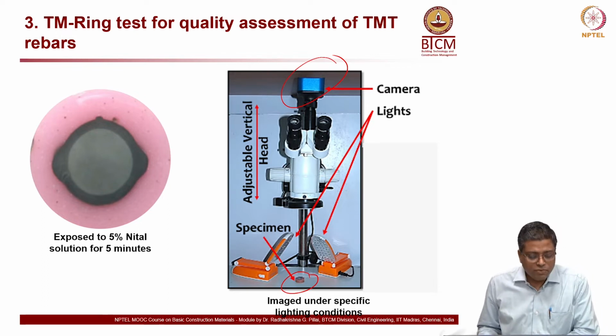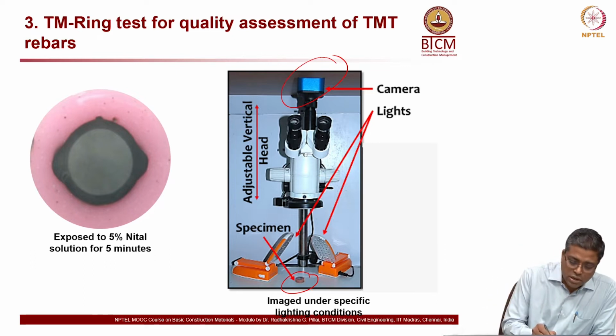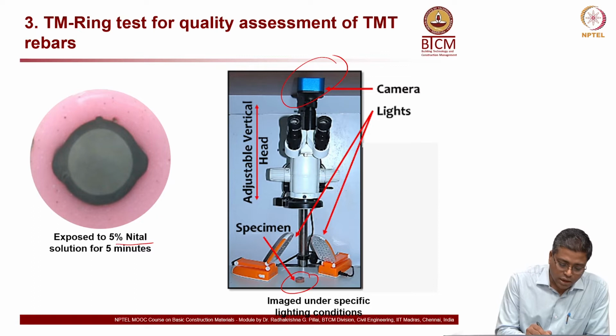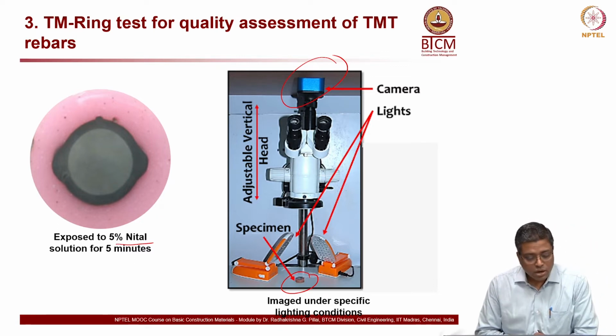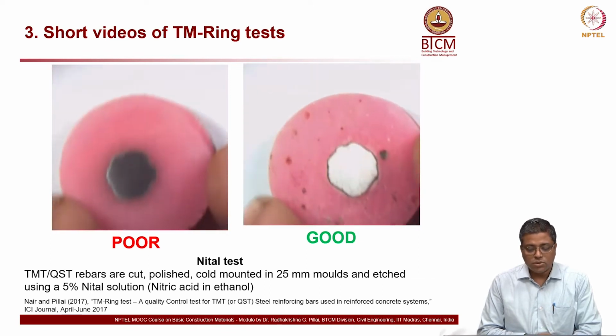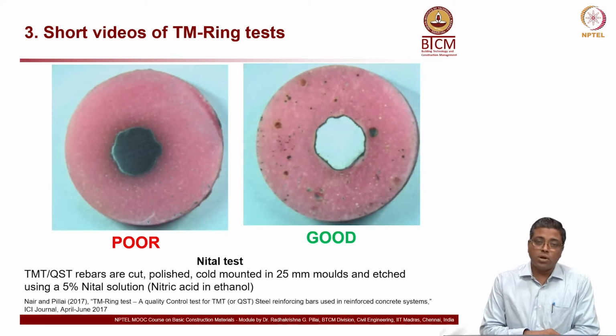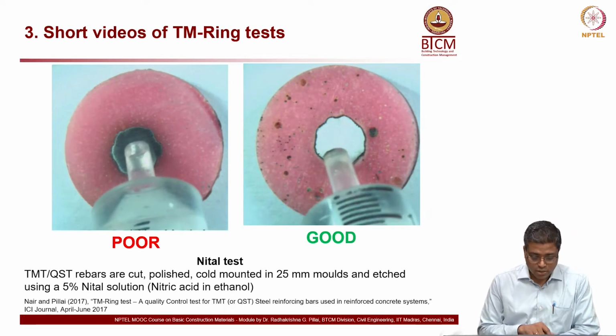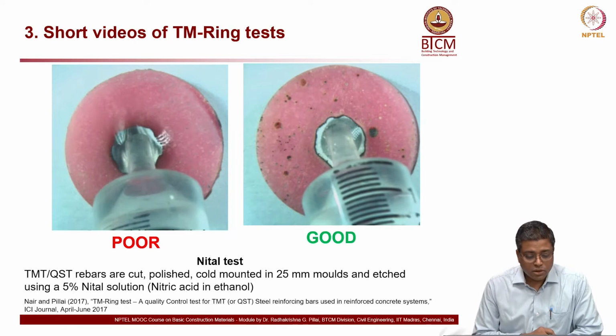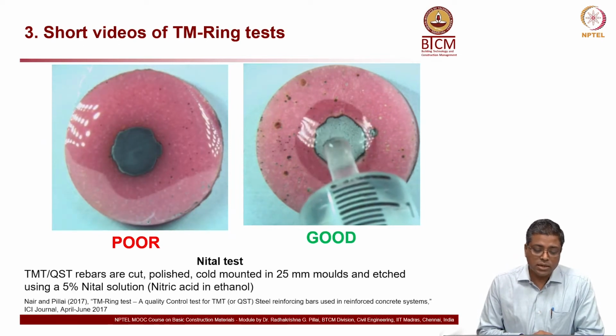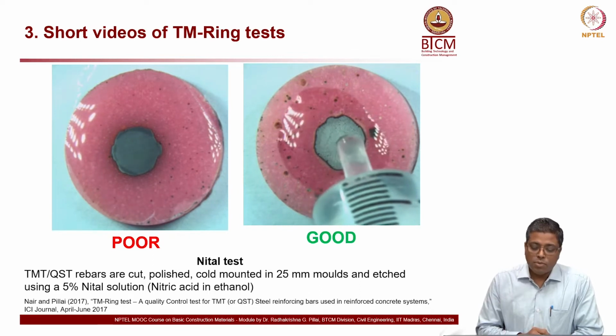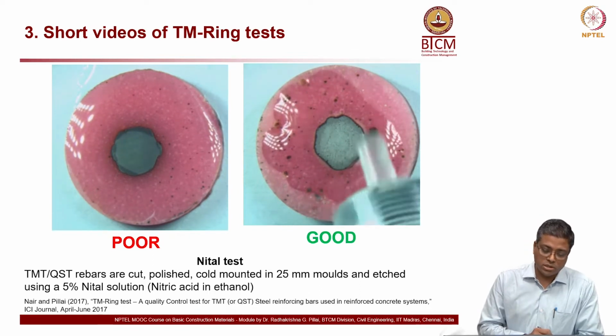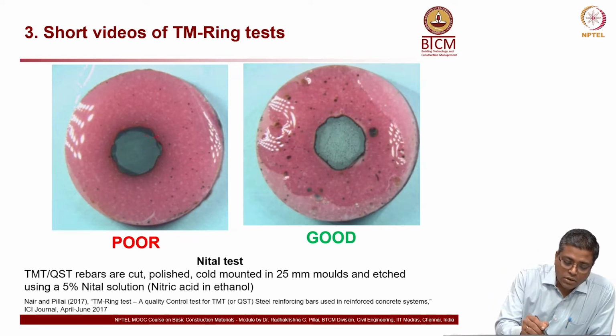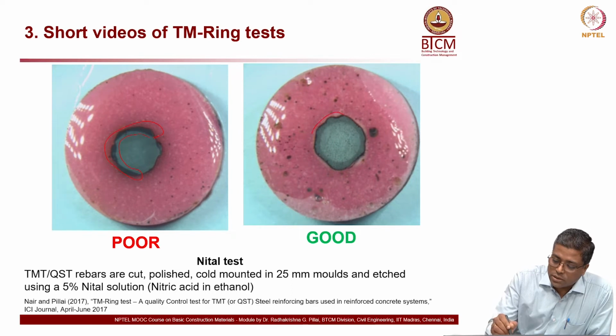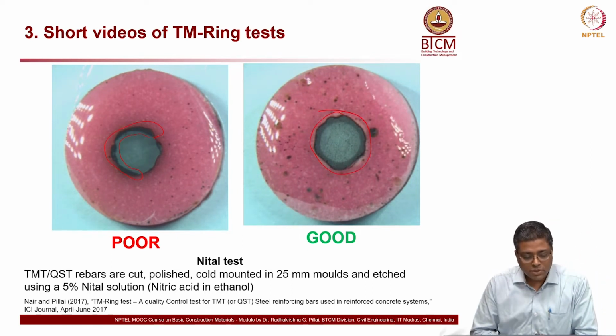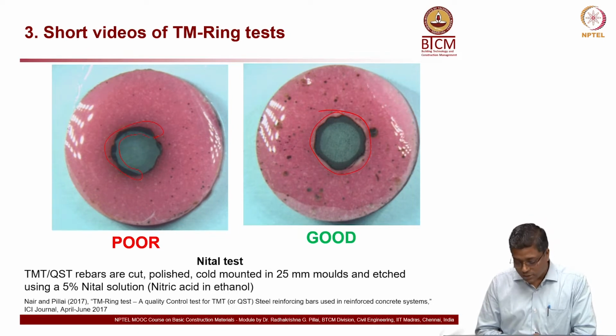So all you need is a 5% nital solution. Nital is nitric acid plus ethanol. You just apply it, and this is the test. You can see the video. The one on the left side is a poor quality bar. The one on the right side is a good quality rebar. On the left side, you will start seeing that the ring formation is very bad. But on the right side, you can see a full ring formation. You can see here on the left side, it's incomplete, no? But on the right side, you have a full ring. Okay, so the left side is a bad quality rebar, the right side is a good quality rebar.